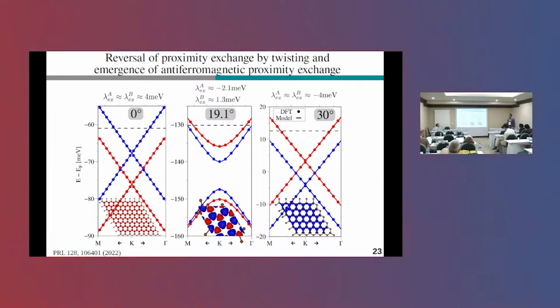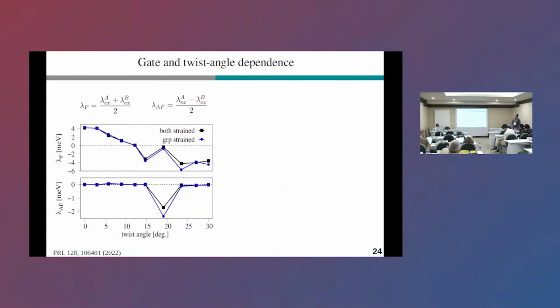And of course we did not only investigate these three angles, we did the full angle range scan, and what I summarize here is, say, the ferromagnetic and antiferromagnetic proximity exchange as a function of the twist angle. And what we can see here is that the ferromagnetic one can be tuned rather nicely from positive to negative values when twisting from 0 to 30 degrees. This antiferromagnetic proximity exchange arises only for this special twist angle of 19.1 degree.